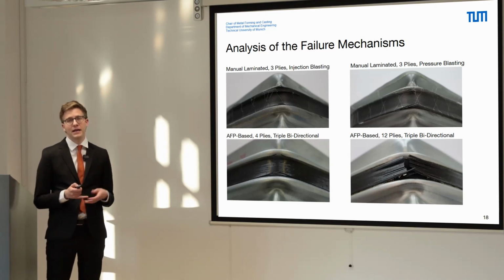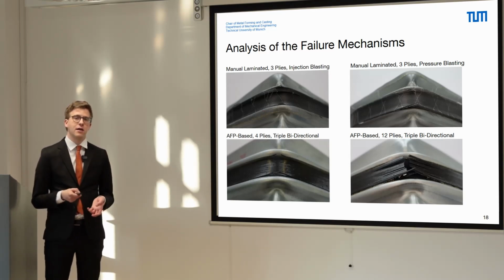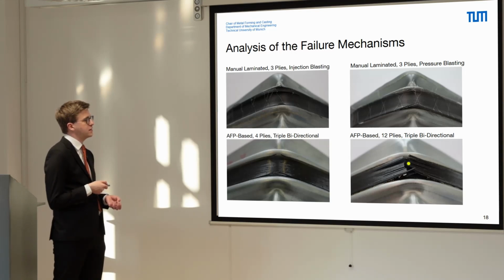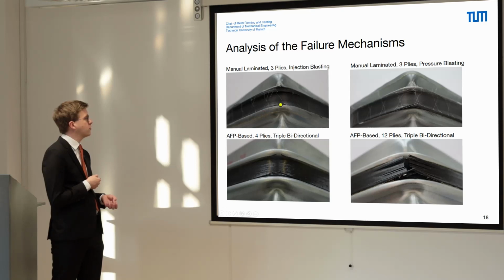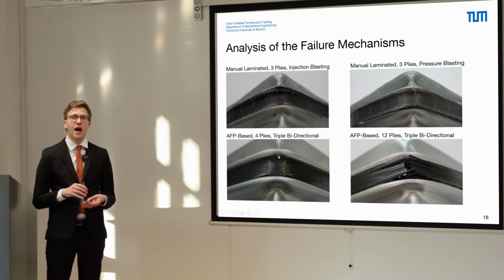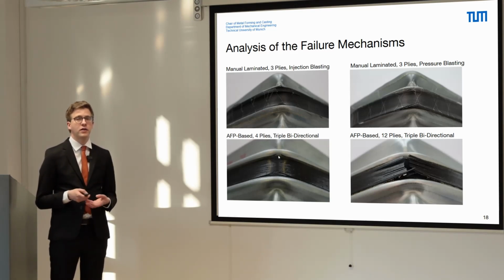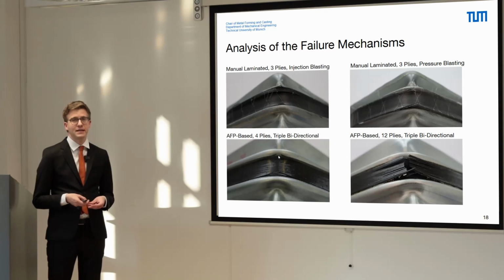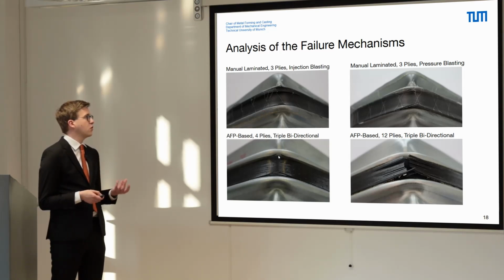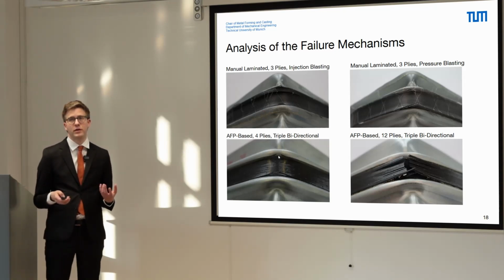Therefore, the mainly appearing failure mechanism was fiber breakage, as shown here, or here in the border region, here again in the border region, and here again in the border region. And it only appeared after the sheet had already undergone significant plastic deformation. So we can conclude that both pre-treatment strategies can result in sufficient results for further application of the hybrid beads.